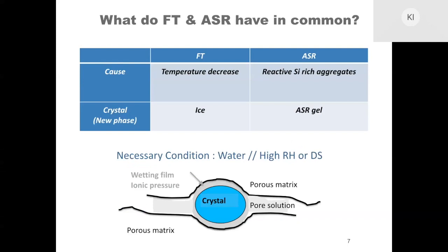So here in this cartoon, you see the reason why we have damage. Here you see a pore of cement, and inside, the blue is the new phase, so the new crystal or solid that is forming. During this process, we have the confinement of the ions between a nanometric layer of the cement and the new phase that is forming. So basically, this confinement of ions is building up an ionic pressure, and this is what is pushing both solid phases. And if the new solid phase is as strong as cement, then the damage starts passing also to the cement phase. So here the new thing is that not only water is important, but also the ions.